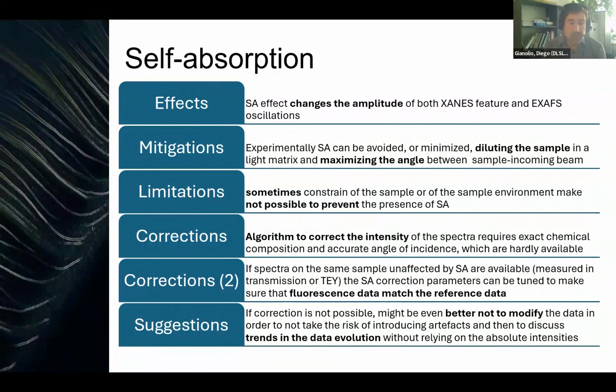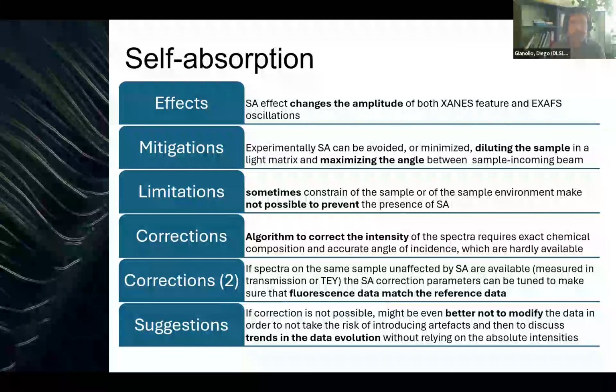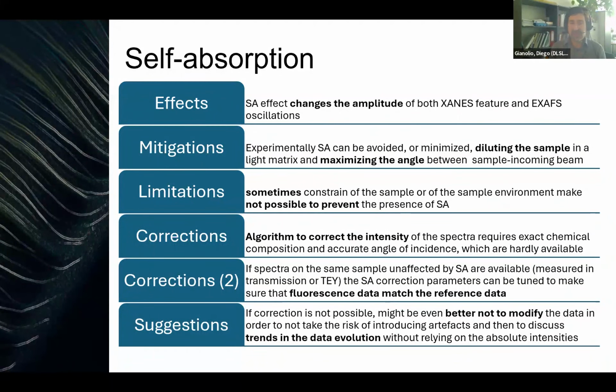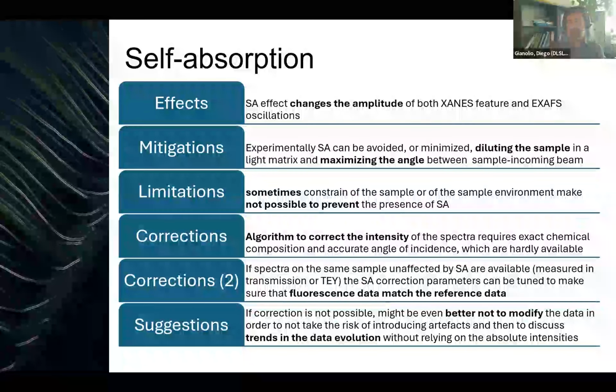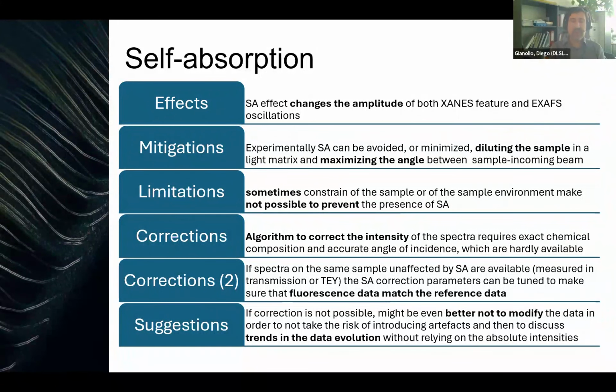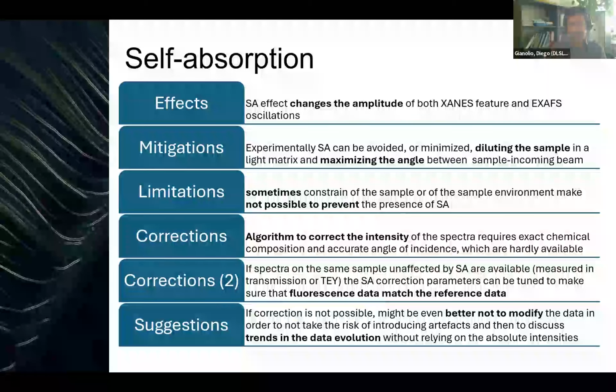If this correction is not possible, within the group, I think we agreed that it's probably better not to try and modify the data just to make them look good, because the risk of introducing artifacts and not obtaining the right result is very high. So it is probably better to discuss trends in the data evolution, for example, if you're following the reaction of a sample or a sample as a function of temperature, without relying on the absolute intensities.